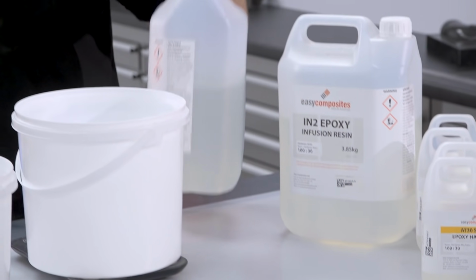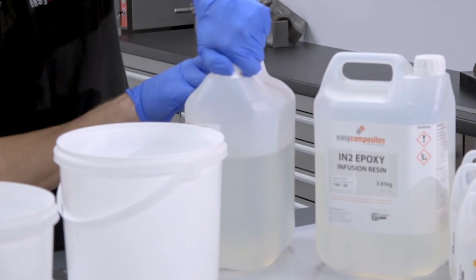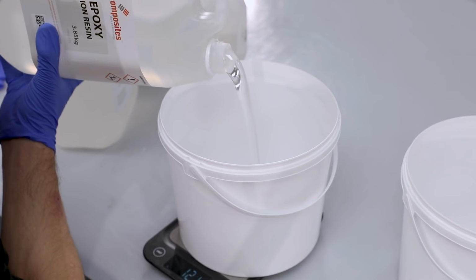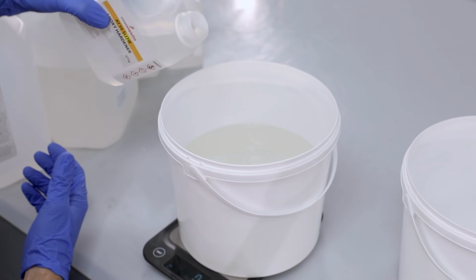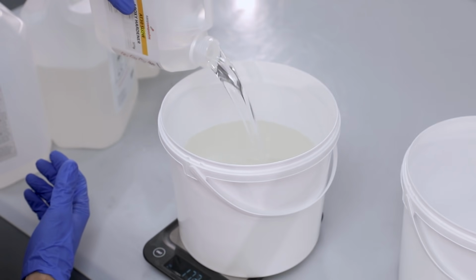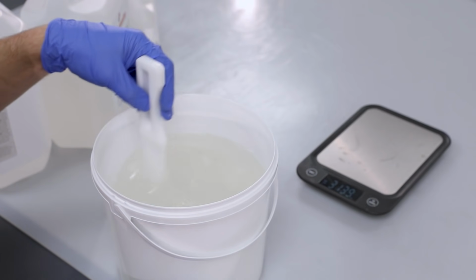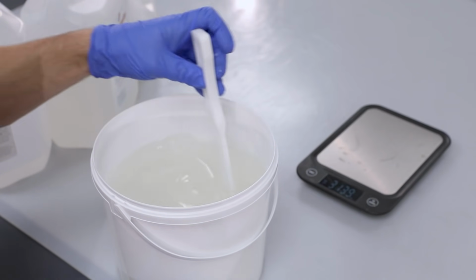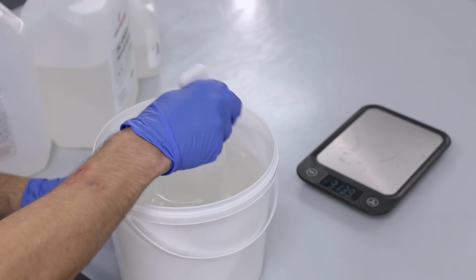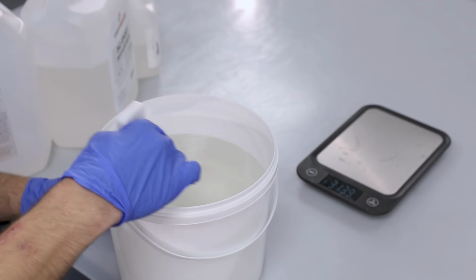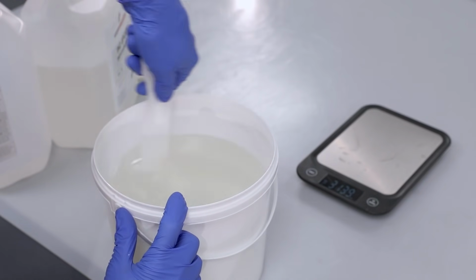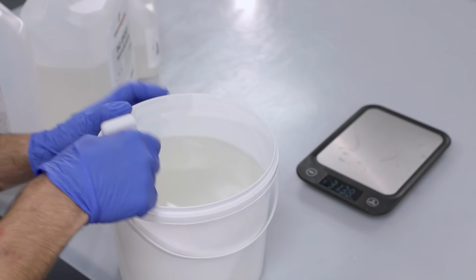So let's get that resin mixed up. Here we are mixing the IN2 epoxy infusion resin accurately and thoroughly to the specified ratio, like you will have seen us do in many other tutorials. In this case, we are mixing the entire amount of resin in one batch, but for larger or slower infusions, using multiple batches as the infusion progresses can help to ensure that you don't run out of pot life.